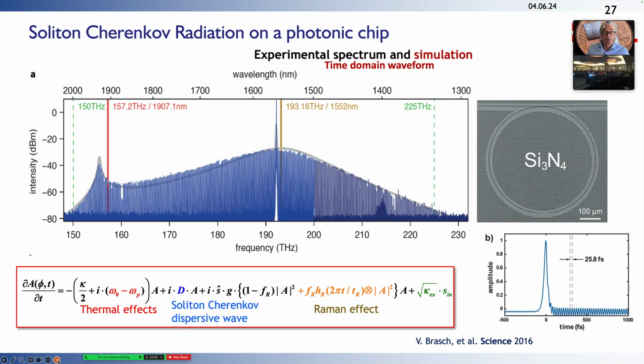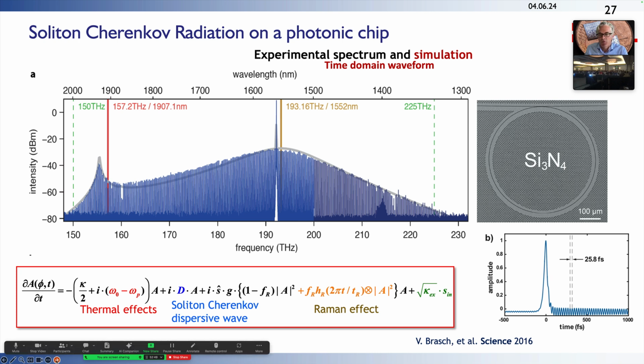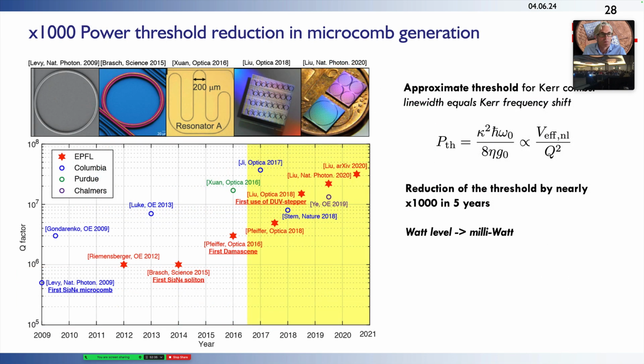And these can be extremely broad in silicon nitride. These are very short pulses, as short as 5 optical cycles, that travel inside the silicon nitride resonator, which we can model very well, and that can produce frequency combs with spacings of tens to hundreds of gigahertz. On the one hand, this allows us to directly synthesize microwaves by detecting the pulse stream, or to use these, for instance, as lines in coherent communication experiments. And due to this reduction of losses over the last years, it has become possible to generate these frequency combs with only a few milliwatts of power, which is about a factor of 1,000 reduction in the last decade.